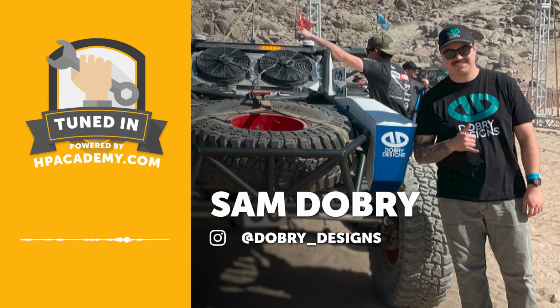Now, it's not going to pass the ASTM standard because that's very process controlled, but from our experience, that yields the best results for the type of tube chassis and various weldments that we're putting together. That still has its limits too, though. There's always going to be a heat affected zone. And for a lot of our parts that get the worst shock loading in the worst cases, we heat treat those, and that changes that whole system.